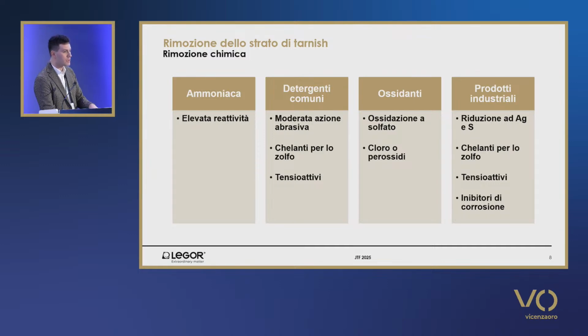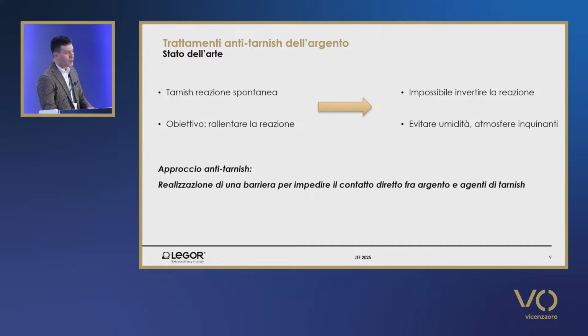And then there are industrial products which use reducing agents which reduce metals. There are chelating agents which bind sulfur, and then corrosion inhibitors which avoid the re-aggression of silver for a long period of time. Now, as a consequence, well, we have said that tarnish is a spontaneous reaction of silver. So even if you remove it, the surface will still be subject to tarnishing. So what you have to do is to slow down or avoid this type of reaction. It's impossible to stop this process.